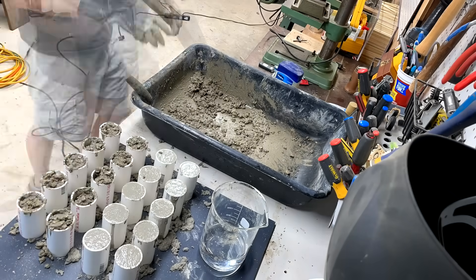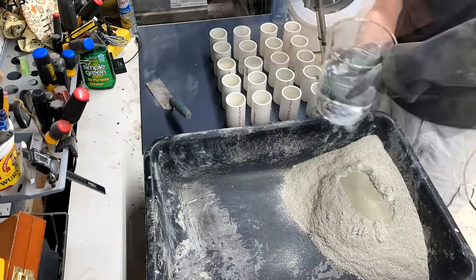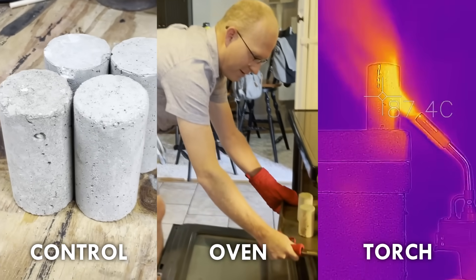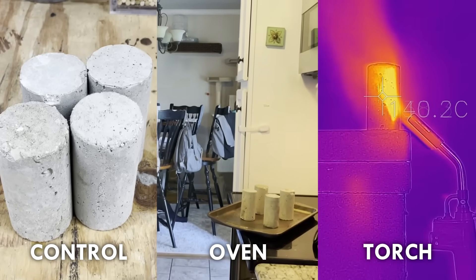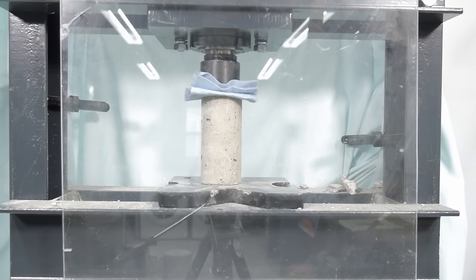What I really want to show you is how concrete heat damage can be more subtle and insidious. I'm making a bunch of cylinders of concrete, and we're going to test their strength after exposure to extreme heat. These samples are just made with regular old Portland cement concrete from a ready mix bag purchased from a home center. I'm also making equivalent samples from a specialty concrete that uses materials resistant to deterioration from high heat — also known as refractory concrete. I'm testing three different scenarios: controls left at room temperature, samples warmed in my oven to 500°F (260°C), and samples blasted using a gas torch. Two types of concrete times three different temperatures times two samples means I have 12 cylinders in all, but I made a few more just in case. Once they've all been heated, except the controls, I let them sit in my garage for a week. Now it's time to break them.